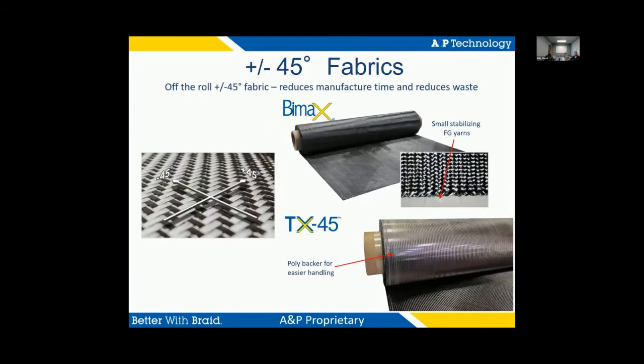I mentioned we have 2 different forms. Bimax, it's very straightforward. It can be pre-pregged readily because we do introduce a small amount of glass axial yarns. So it has a high level of conformability, but is still able to be managed by hand without distorting all over the place. If you do need a higher level of drapeability, we do have TX45, which comes on a poly backer.